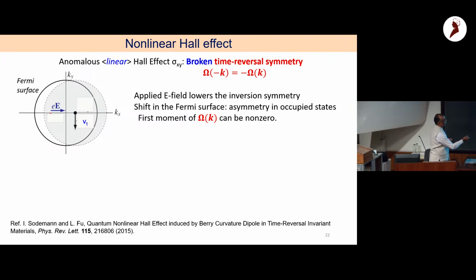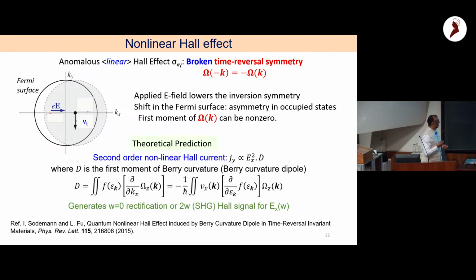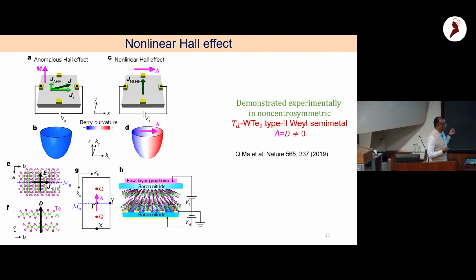And that can give rise to, for example, a first moment in reciprocal space of Berry curvature, which can be non-zero. This was a theoretical prediction by Inti Sodemann and Liang Fu, which showed that D, the Berry curvature dipole, a new quantity I'm introducing here, which is essentially the first moment of Berry curvature in reciprocal space, if non-zero, generates either rectification or a second-order Hall effect, meaning the Hall current Jy is a quadratic function of Ex, Ex squared, times the Berry curvature dipole. It means you apply an electric field at a frequency omega, and the Hall effect arises at 2 omega or zero frequency. So this is the take-home message, and this is very nice because this lifts some of the symmetry constraints that we had earlier.